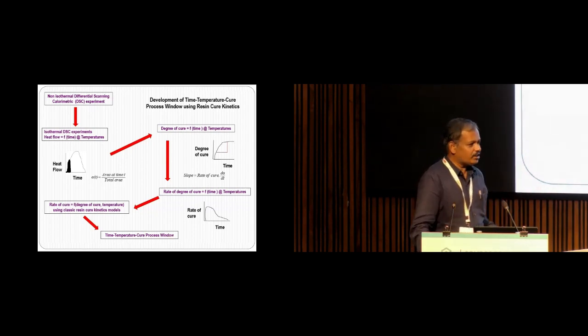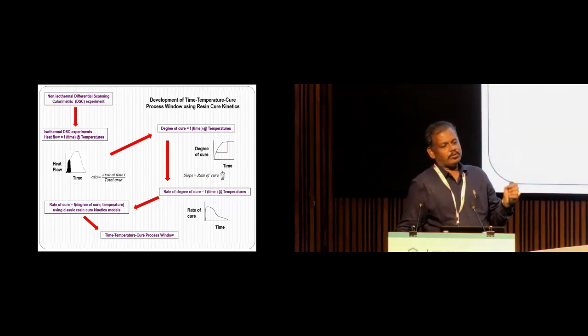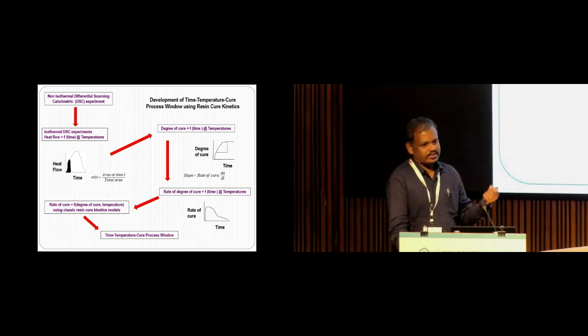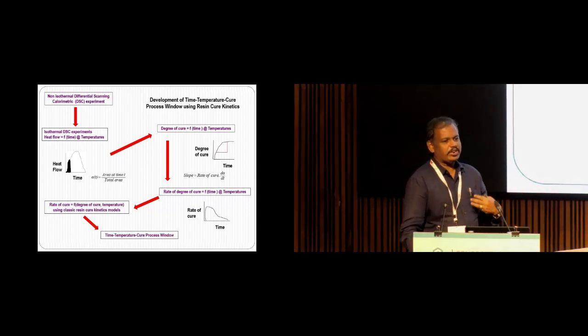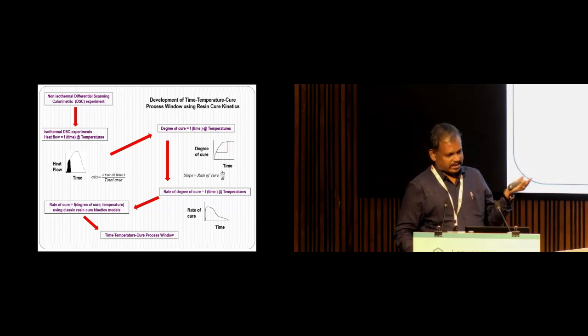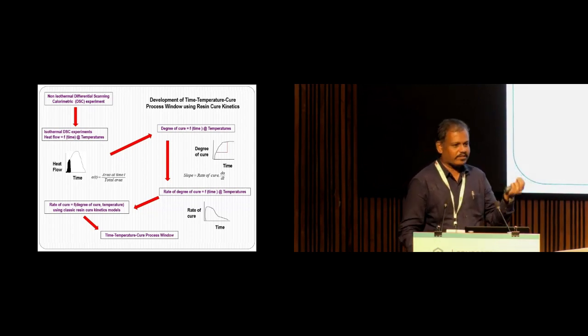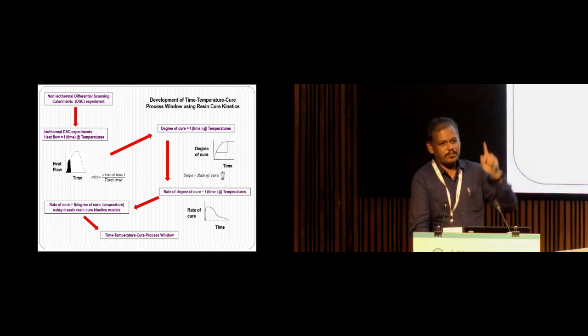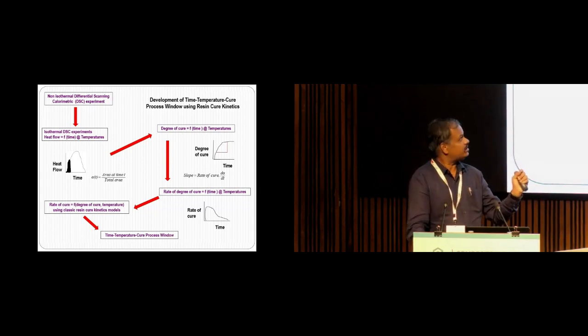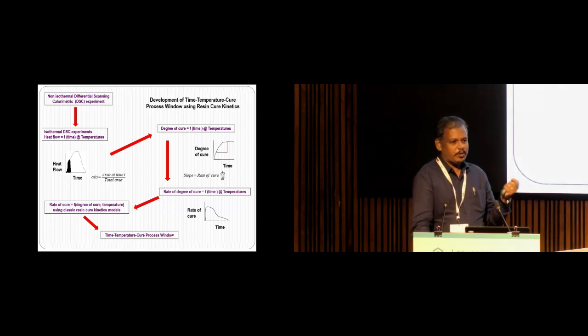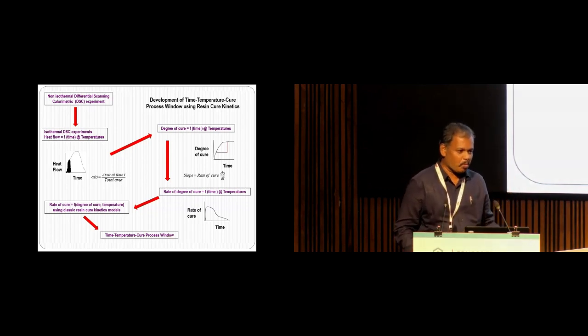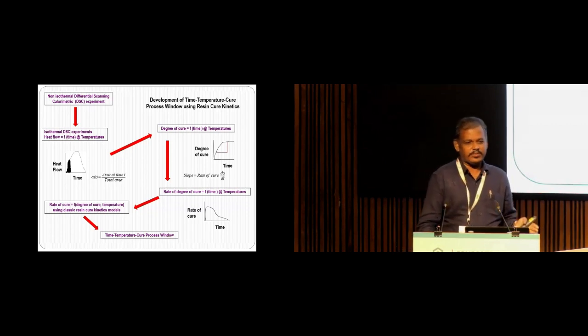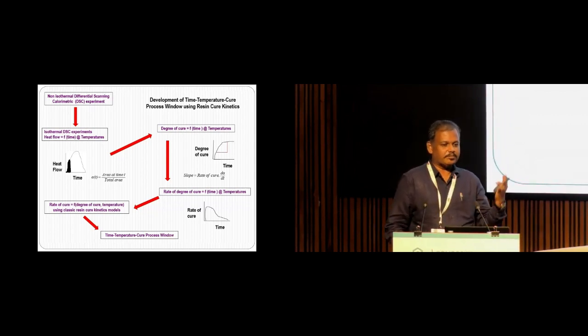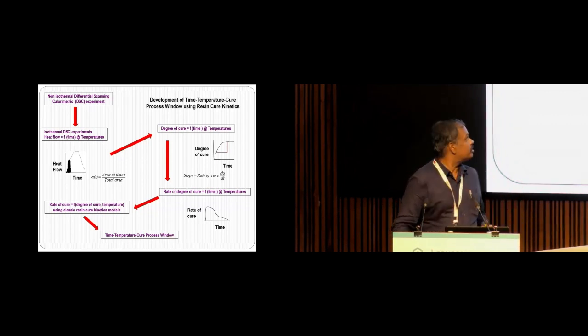There is another reason behind it. When I perform at a temperature lesser than the onset temperature in DSC, it takes a lot of time to complete the curing reaction, so the sample has to be retained within the DSC sample holder for hours. But when I keep the temperature more than the peak temperature, before the DSC machine senses the heat flow, substantial reaction might have been completed. So obviously you should select at least 4 to 5 temperatures between the onset cure temperature and the peak cure temperature.